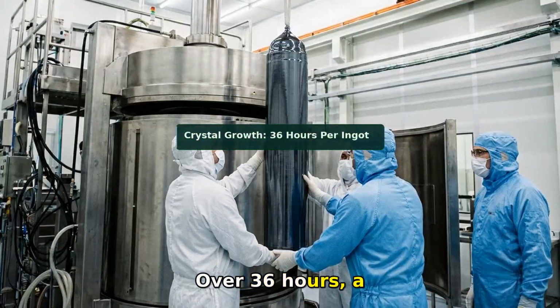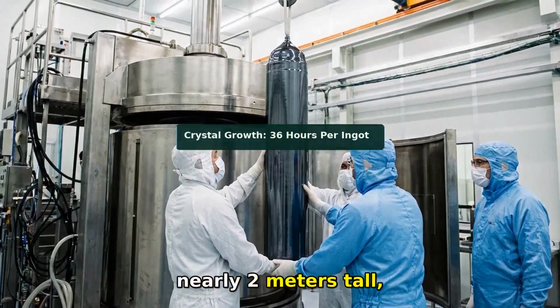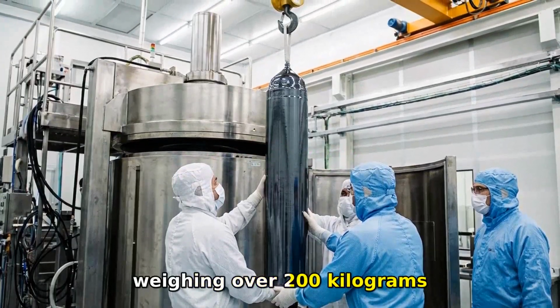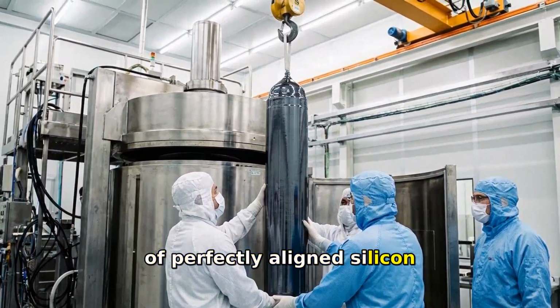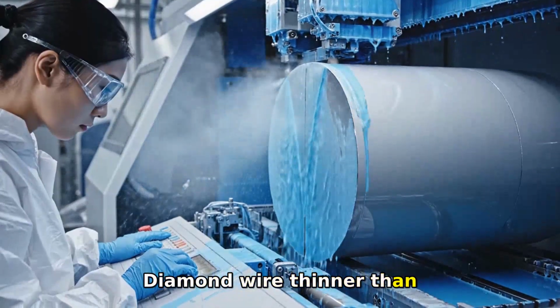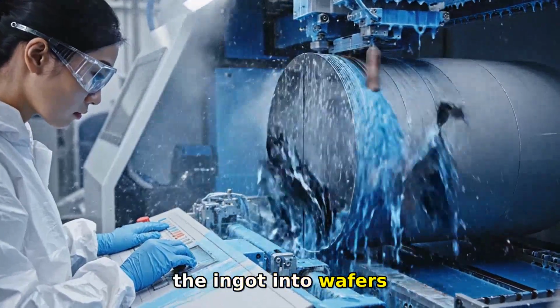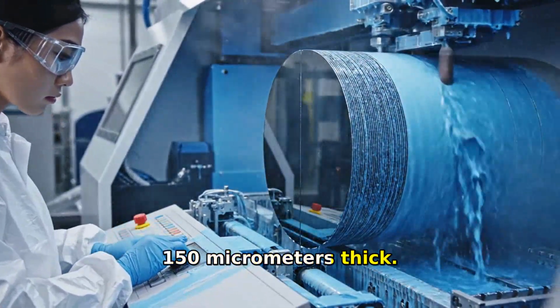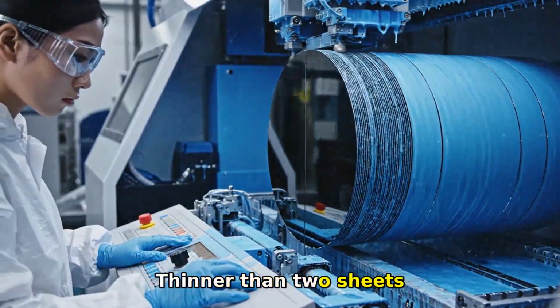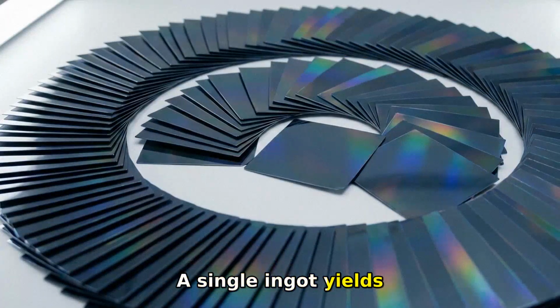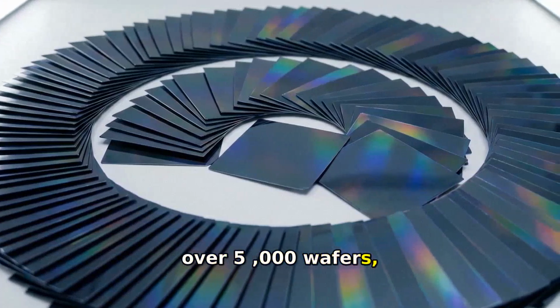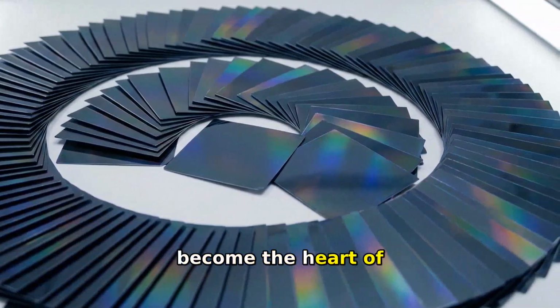Over 36 hours, a single ingot grows to nearly 2 meters tall, weighing over 200 kilograms of perfectly aligned silicon atoms. Diamond wire thinner than a human hair slices the ingot into wafers 150 micrometers thick, thinner than 2 sheets of paper. A single ingot yields over 5,000 wafers, each one destined to become the heart of a solar cell.